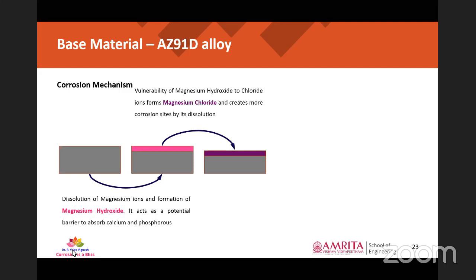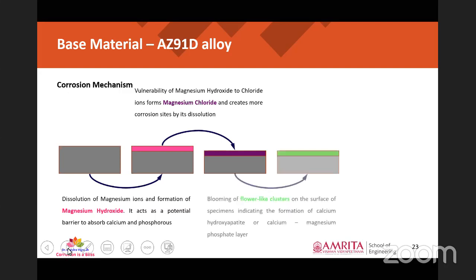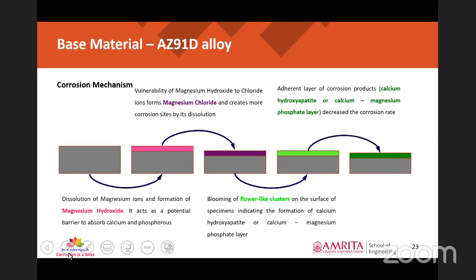So next this forms flower like clusters. Those flower like clusters are just phosphate salts of calcium and magnesium, and these phosphate salts are nothing but the hydroxyapatite crystals. So the formation of such crystals over a period of time, that is after 7 days of immersion, confirms that there is an adherent layer of corrosion products based on calcium hydroxyapatite or calcium magnesium phosphate layer, which is very much essential for implant based applications. Yeah, so this is how the big picture is.